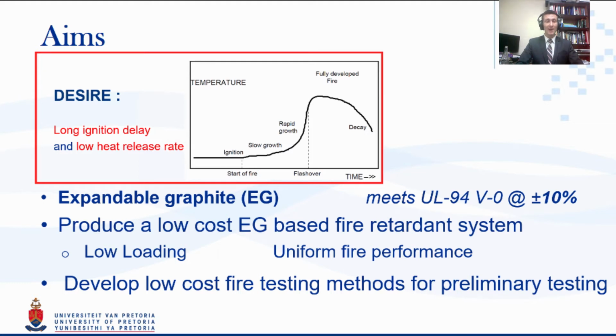One of the reasons for that is that as it expands, it creates strings, and these strings, when attacked from above, go out and then lay down on the material, making a thermal shield. They also make a good barrier from the side by falling against the material.